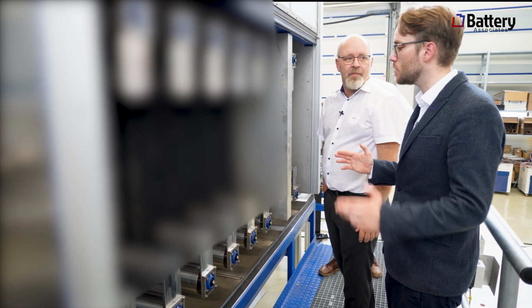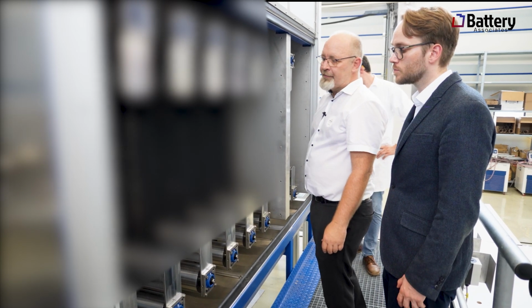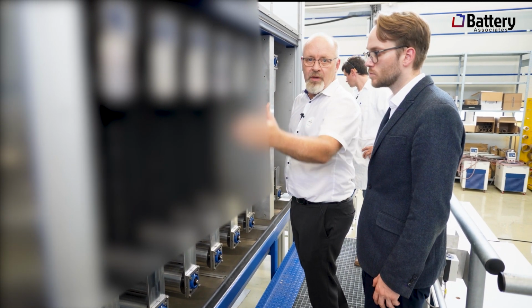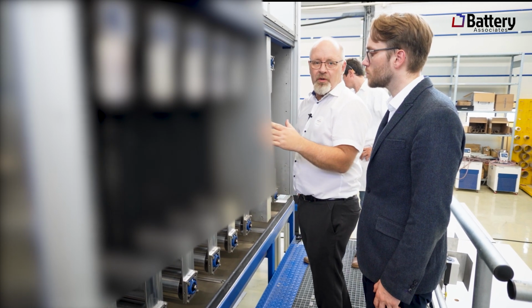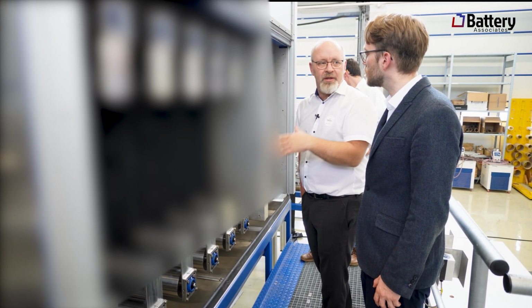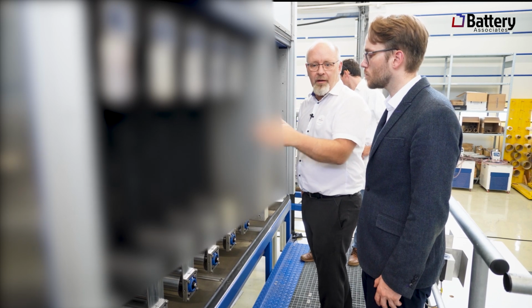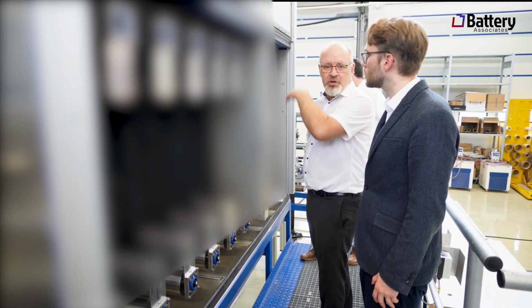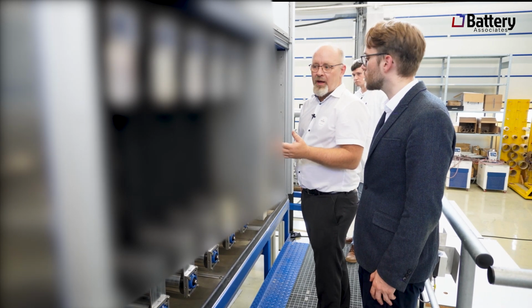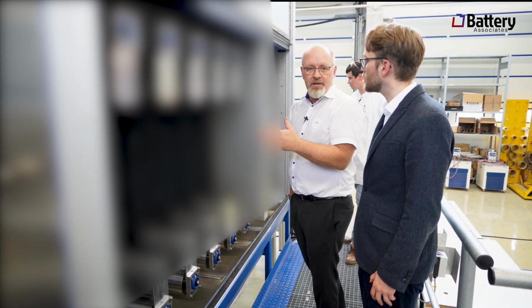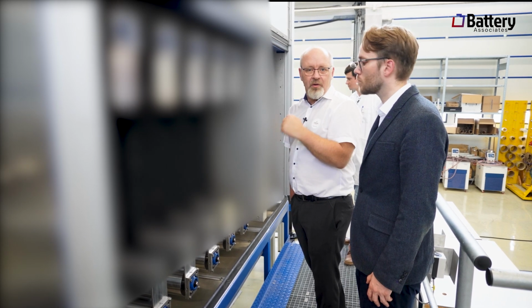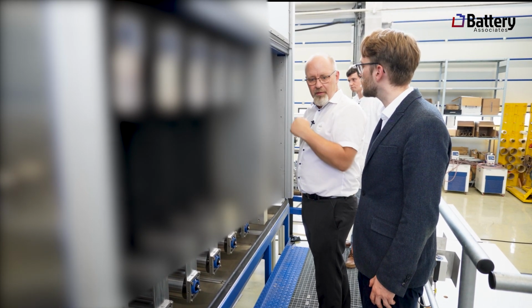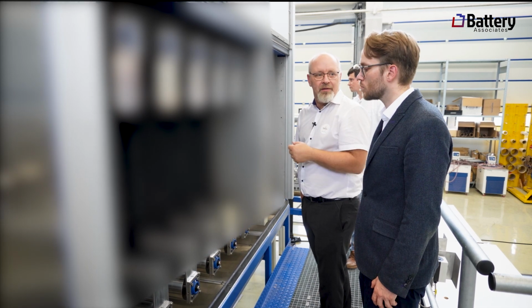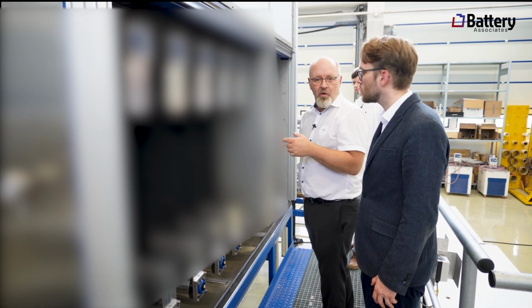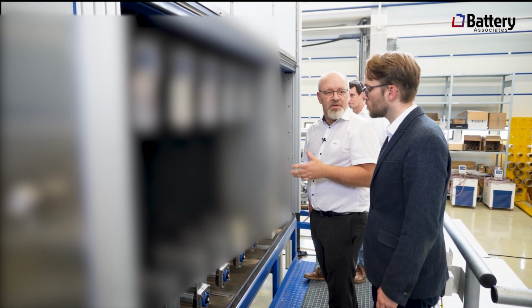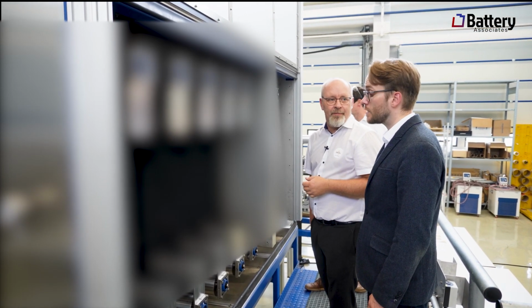So space, of course, is an obvious one. Is there also an energy benefit? Sure. All the solvent is in the water. We do not have to dry off solvent, so we do not have to take care of any flash points, or of taking the solvent out again from this huge gas flow, and therefore it's much more energy saving. The water can be taken out in a very concentrated form, and the energy can be kept back and recycled in the drying step. And therefore, we assume that we save up to 80% of the energy compared to the wet coating process. That's a really impressive number.